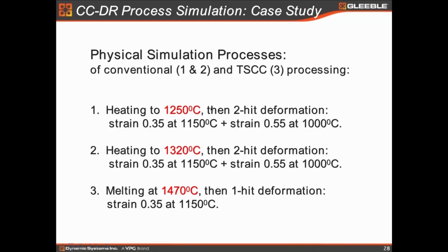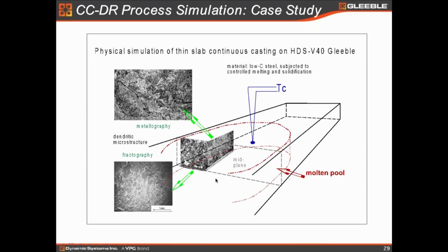One is we'll heat up to 1250 with two hits, at 0.35 at 1150 and 0.55 strain at 1000 C. And the second one will heat up to 1320 with the same two deformations. And the third one heats up to 1470 to melt the sample and do just one hit at 1150 and 0.35 strain. So we will cut the specimen crosswise, we call it the middle plane, and in the longitudinal direction to see the microstructure.